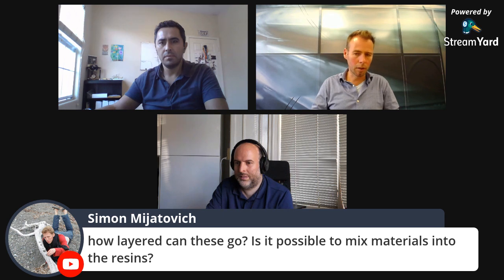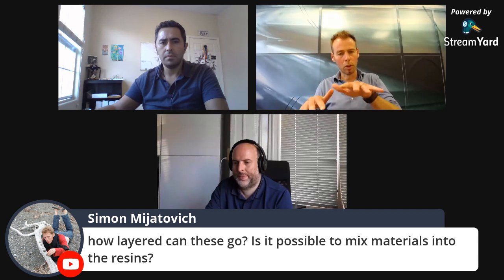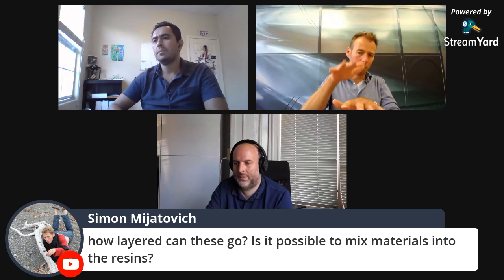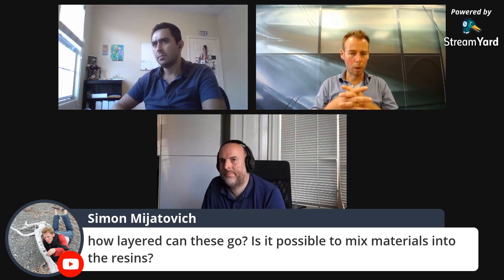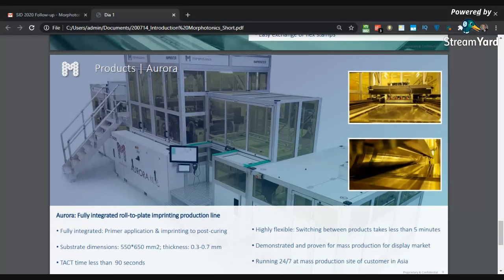Yeah, I can think of a few applications, or you could try to make it conductive. You can also indeed build a multi-layer stack. For instance, you have a first layer, you planarize it, and you build a second layer on top. This is well possible, but as again, it sounds all simple, but the devil is in the details. The expansion coefficients of these layers must well match, and durabilities of these stacks need to be tested.